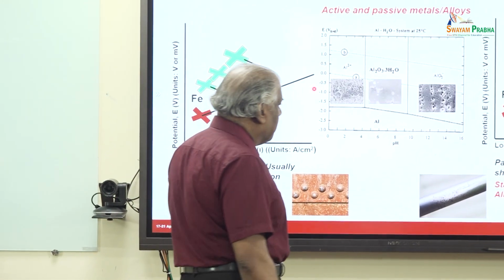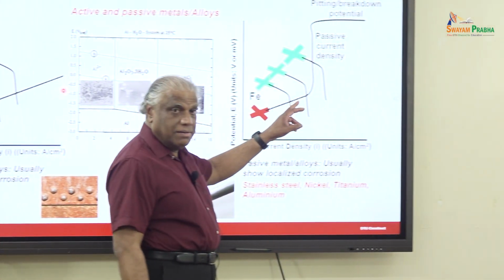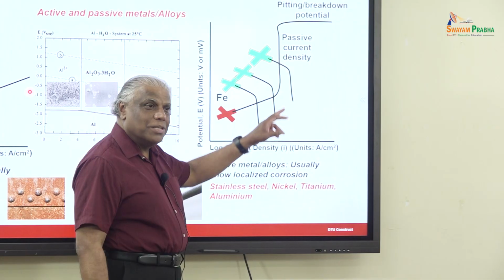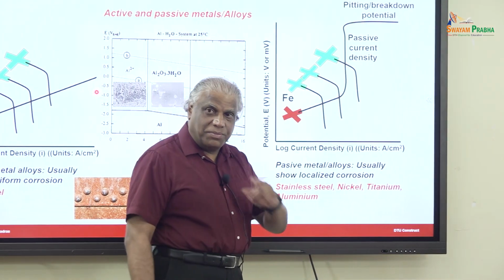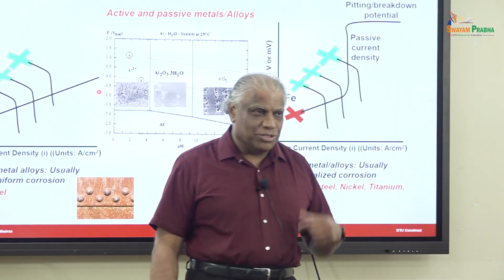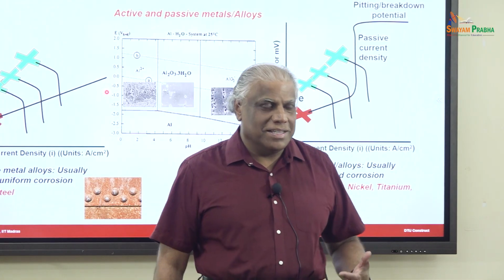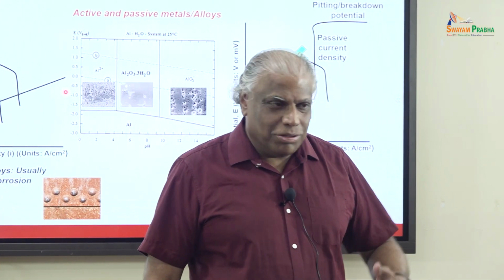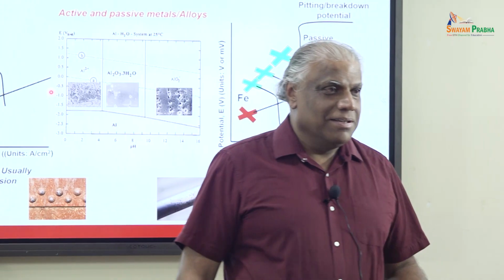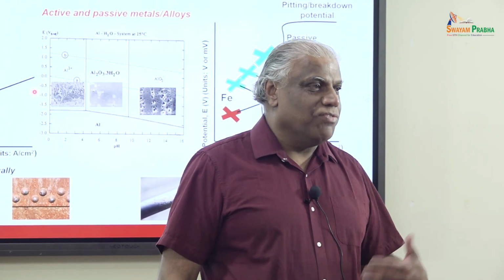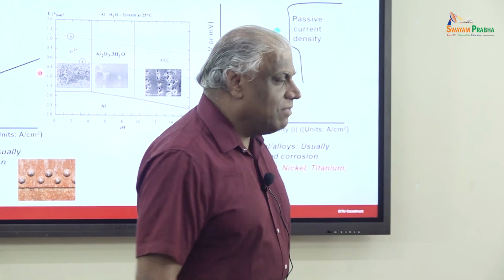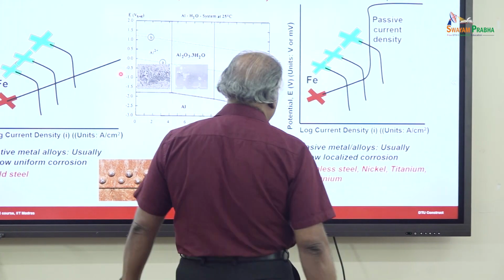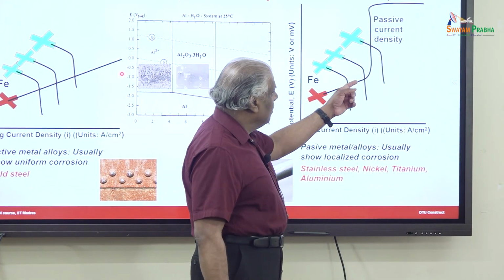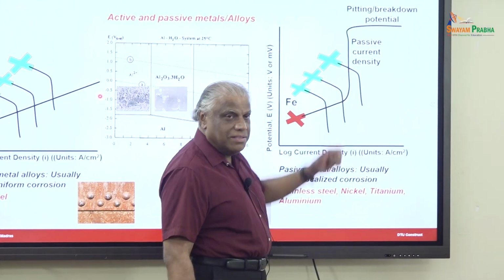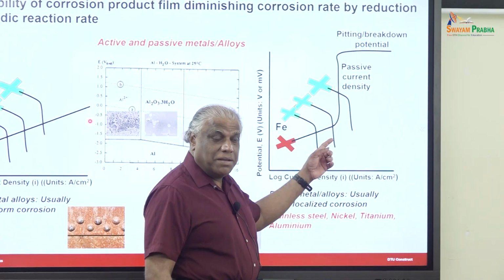But on the other hand, you look at here, that is a passive metal, actually increasing the oxygen concentration is good. This is what Lakshman was also saying yesterday, because you need to think that passivation is an oxidation of the surface, oxygen is an oxidizing agent, and if there is more oxygen, you can form the oxide better, and that way having more oxygen in this case actually shifts this potential to the passive region, and in this case it is good. Actually you can make use of this, right?